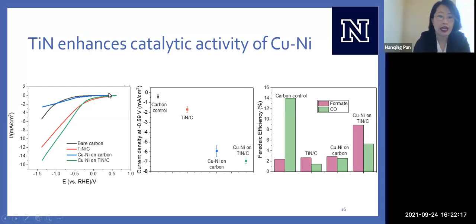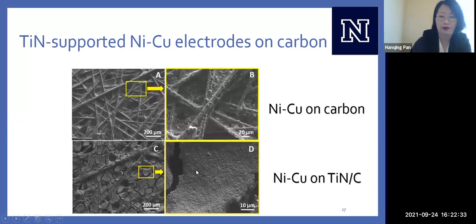So again, we're looking at current density and onset potential. And so I'll point out that our copper nickel catalyst on top of the titanium nitride on top of carbon is giving the highest catalytic efficiency, giving the most products. And I just love looking at these images. They're so fun to look at. But the top here is only nickel copper on carbon paper. And so we're seeing something that was very similar to before.